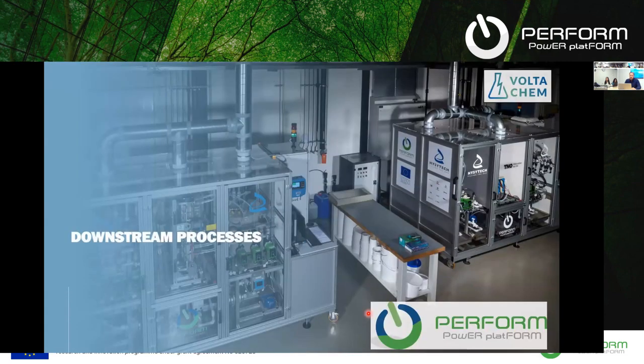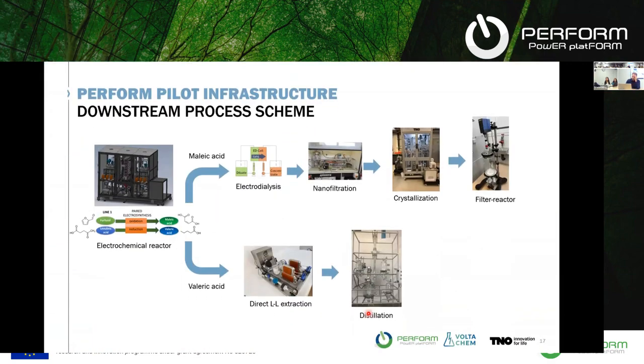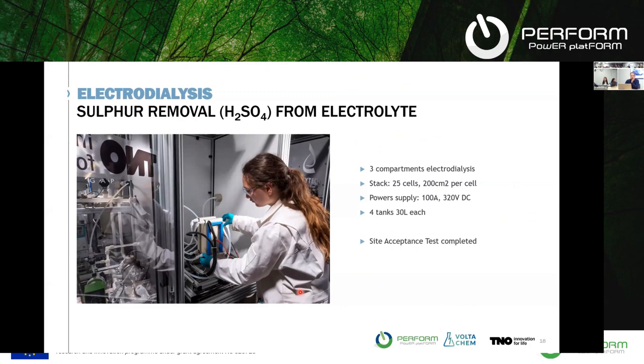Once you have your chemicals in solution, you also need to care about how to get them out and how to purify them. Within the Perform project, we also looked at all the downstream processes to go from the actual electrolyte to the pure compounds. This is the process scheme that we developed. On the maleic acid side, the first step would be an electrodialysis, then a nanofiltration and a crystallization, and then we have the pure maleic acid. On the valeric acid side, we have a liquid extraction, because valeric acid is a liquid, not a solid, and then we have a distillation step.